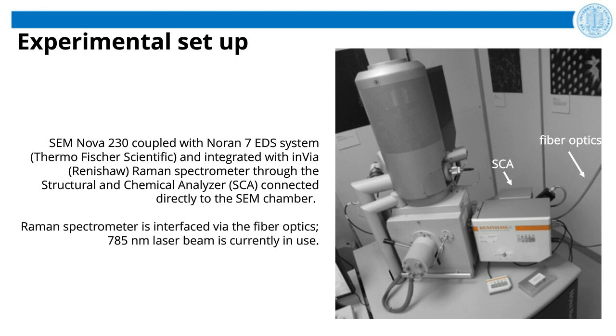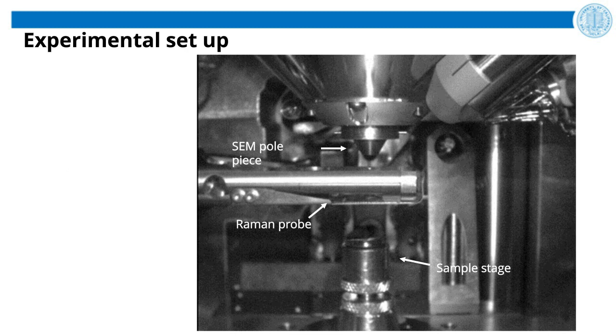The next slide shows the SEM infrared camera image of the inside of the SEM chamber with the pole piece of the SEM, the Raman probe when it is introduced inside the chamber, and the standard SEM sample stage. And when we apply the system with the Fusion heating stage from Protochips, this slide shows that the bracket of the heating stage can be replaced instead of the standard SEM stage basically in a few minutes.